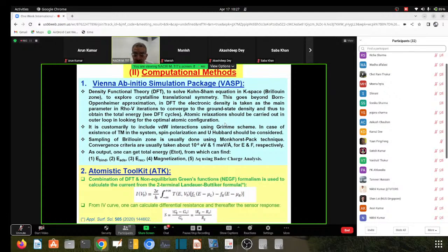On the other hand, the Atomistix Toolkit is very relevant for transport calculation. So they complement each other. Therefore for electronic structures, it is best to use VASP. It's a very popular package, so definitely without any competition. Whereas Atomistix Toolkit is maybe the only one relevant for transport. It calculates transport based on a combination of DFT and non-equilibrium Green's functions. And it deals with the two-terminal Landauer-Büttiker formula, and it's shown there. From the IV curve, one calculates the differential resistance, and thereafter the sensor response. Okay, we have some works published about that, maybe in Applied Surface Science from my group, and of course there you can find more references which are more original.